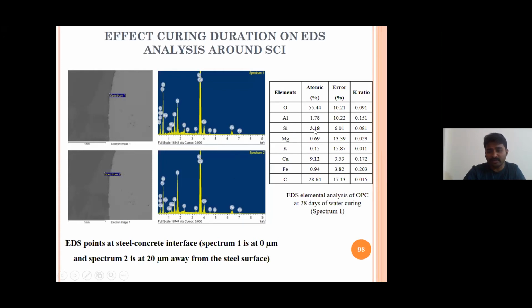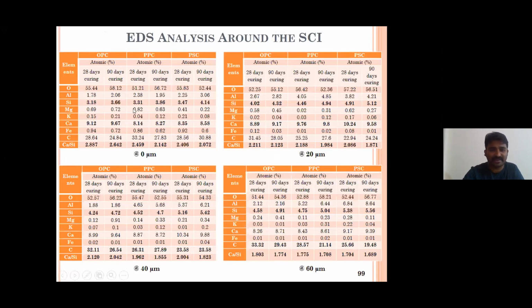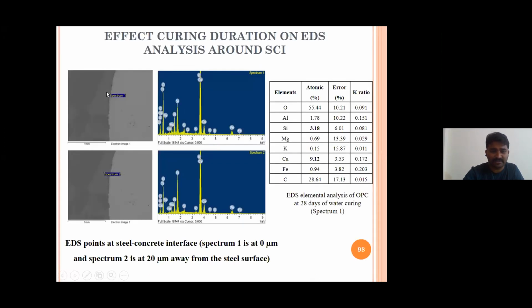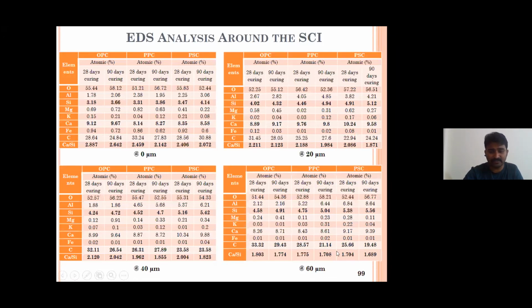See here, the silicon content is 3.18 and calcium content is 9.12. Right? So if I just do a Ca by Si ratio, what will happen? These are the values that we can get at 0 micrometer distance, at 20 micrometer distance, 40 and 60. Likewise, if we increase to 40 and 60, we will get different elemental maps, and the results are shown here: 0, 20, 40, 60.